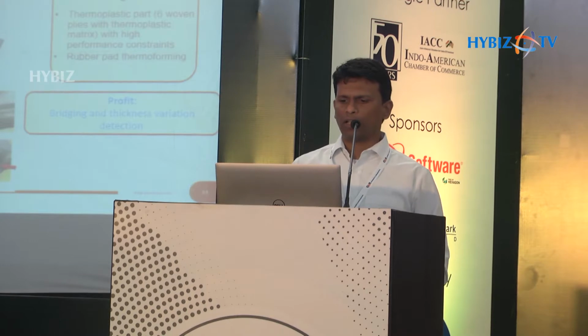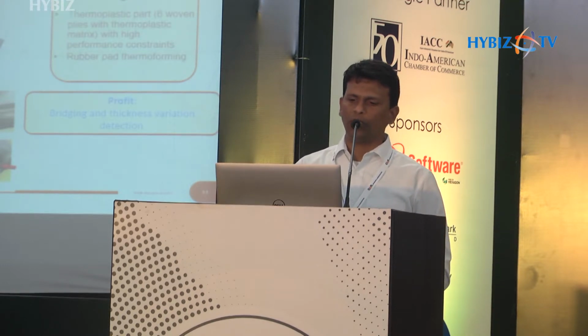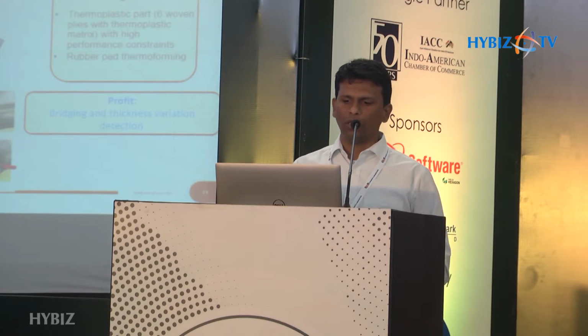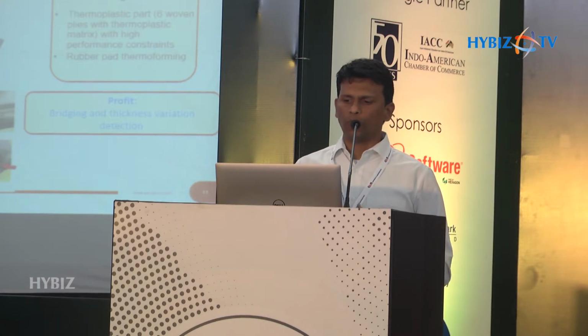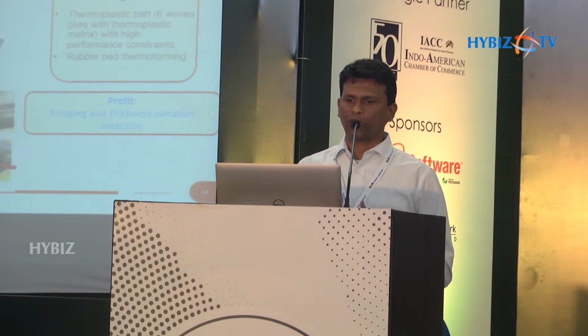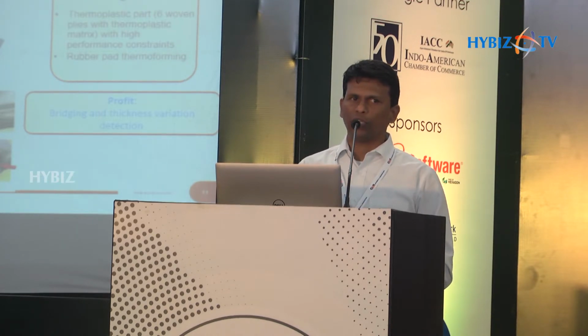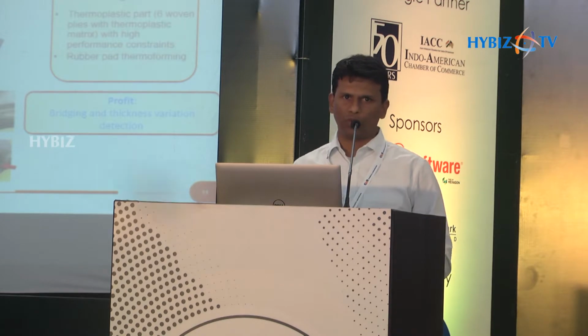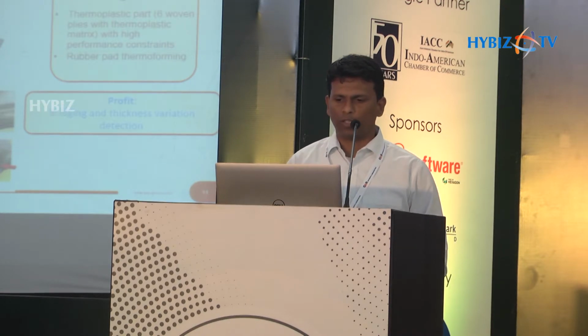So in this they were actually trying to do this complete simulation, and then they were able to see the shearing effects that is coming on the woven fabrics, and then the bridging, and then the gaps that comes in between each fibers, and also the thickness variation detection were diagnosed, which was very much with respect to the reality.